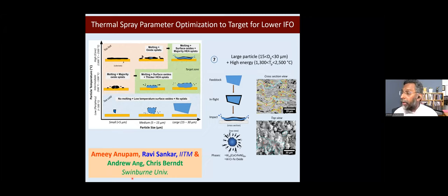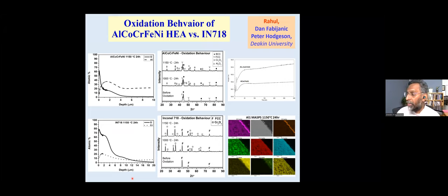We also did what is called oxidation behavior, because at high temperature, one of the problems is that the alloys get oxidized. We want to compare with the conventional alloys that are known, which are called superalloys, and see whether our alloys are better than the superalloys. And we find that they are significantly better than the conventional superalloys in terms of their kinetics of oxidation, and their oxidation resistance is exceedingly high. This has already been patented, and Boeing and Pratt & Whitney are very keen on developing these materials as a new generation of turbine materials for aircraft engines. So a lot of interesting stuff is happening.